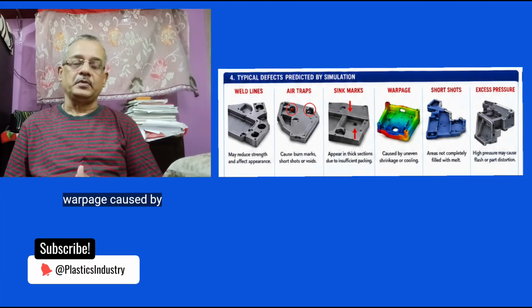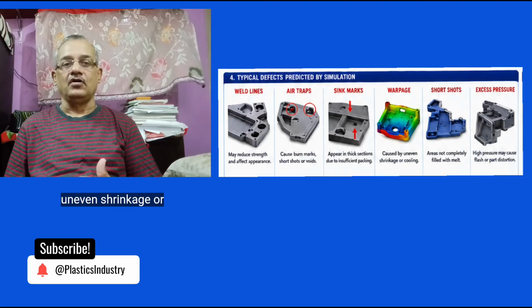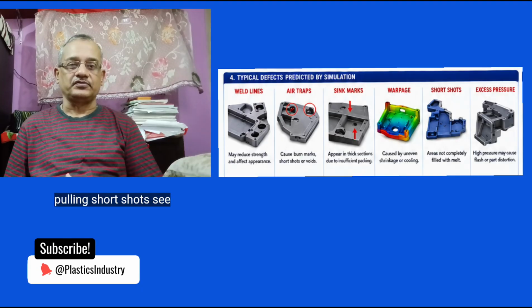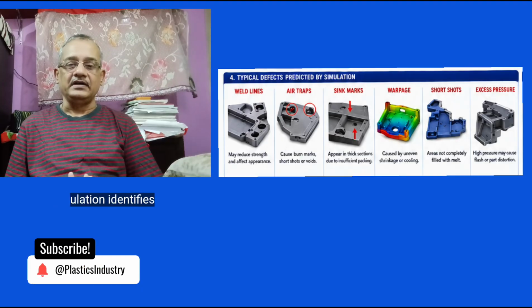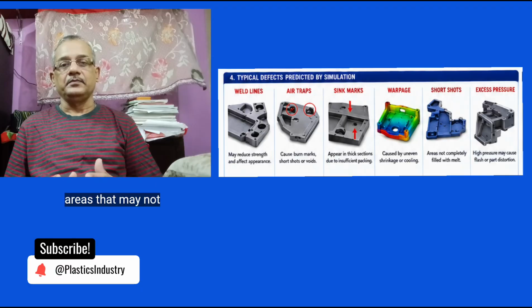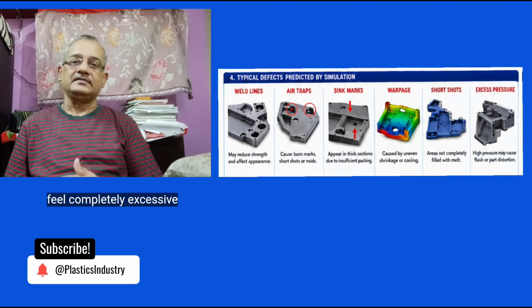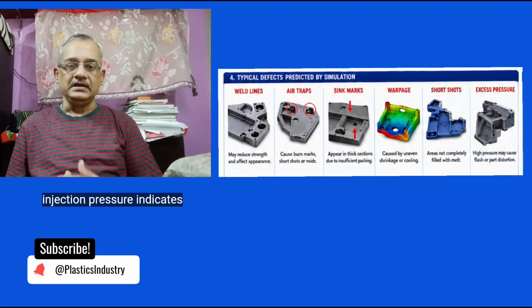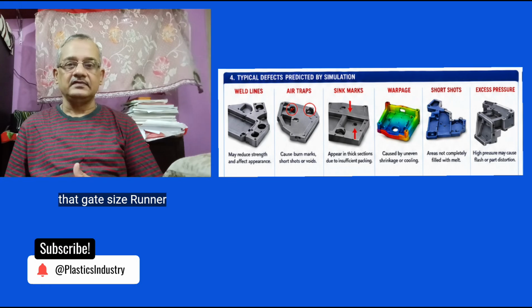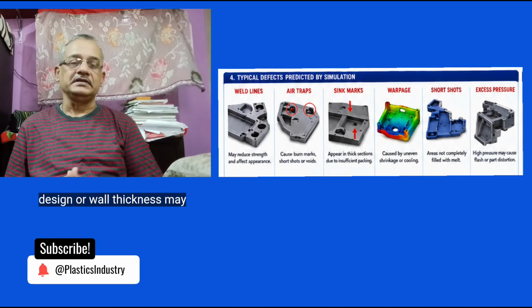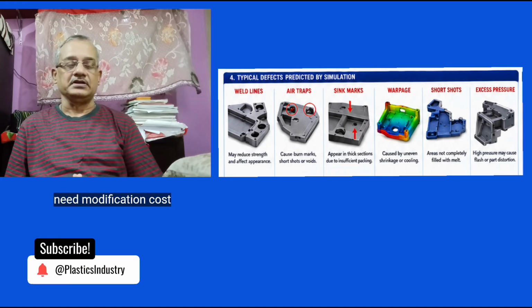Warpage is caused by uneven shrinkage or cooling. Shorts: simulation identifies areas that may not fill completely. Excessive injection pressure indicates that gate size, runner design, or wall thickness may need modification.